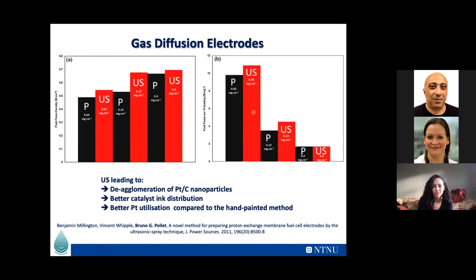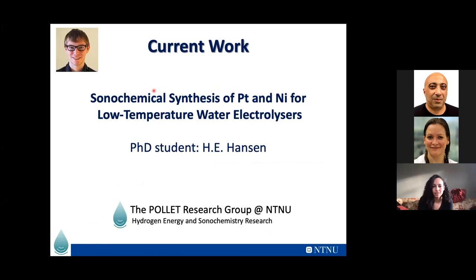Okay, this is another example here, where again, as I was saying early on, we got a better catalyst ink distribution, better platinum utilization, and we could get a peak power density on par with those with no ultrasound, even at low loading. Okay, so 0.4 milligram per square centimeter compared to 0.15, and the peak power density was even slightly better than those with no ultrasound.